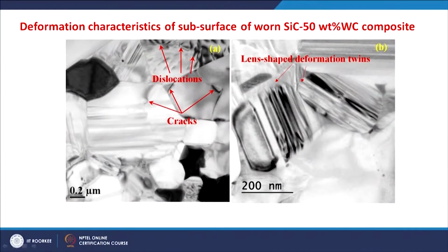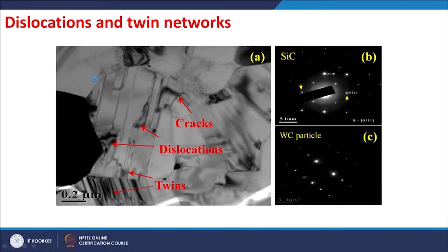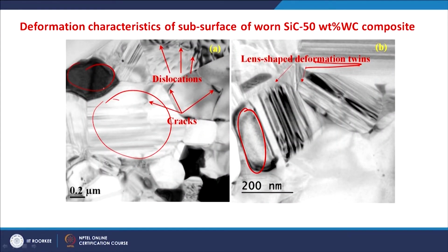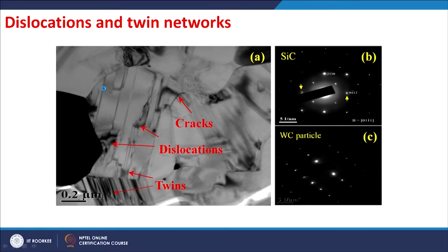As we know, silicon carbide ceramics have a very small number of slip systems. It is quite possible the deformation happens by the formation of these twins. The shape of these twins indicates the lens shape, which indicates deformation induced twins. So, you can see on the grains of the silicon carbide, the cracks and the dislocations are present, whereas the dislocations are not present in the tungsten carbide or at the interface of the tungsten carbide and silicon carbide.